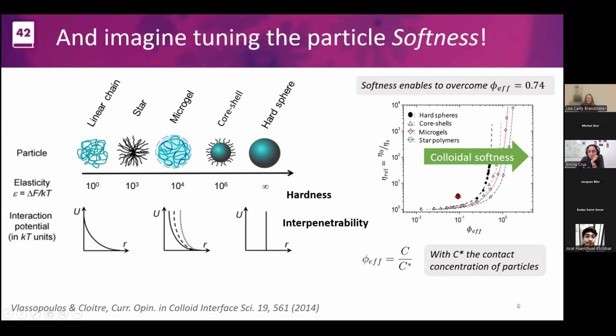So it's good to keep in mind this kind of scheme, because I'm going to show it again later. And what you can see here is that you have the volume fraction on the x-axis, and then you have the viscosity. And the viscosity, you see that at some point diverges to infinity, like we said, for hard spheres. So it's the glass transition. And also we can keep in mind this concept that we're going to introduce, which is c*, the contact concentration of particles. So meaning the concentration at which all the colloids are touching and are filling the space fully. But now, because we can deform the particles, we can prepare higher concentrations. Let's keep in mind that c* is the concentration at which they are all touching.